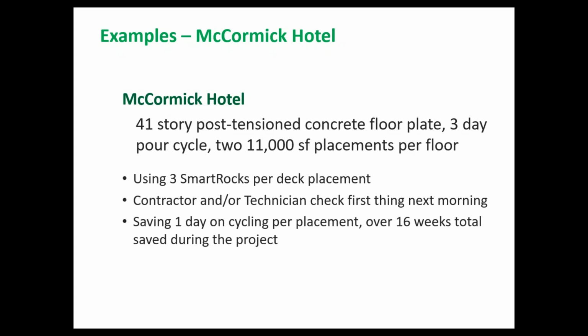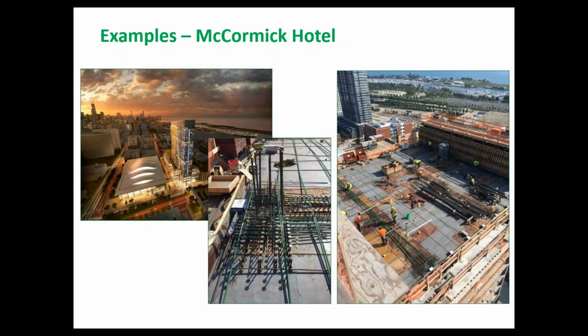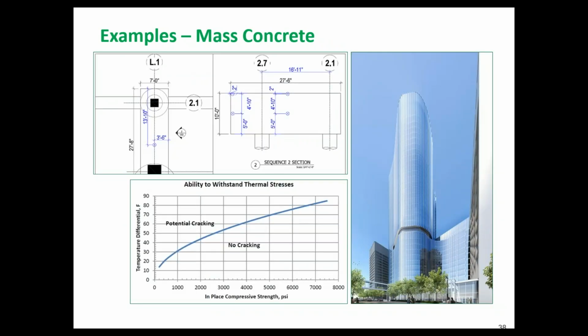That information helped them save at least 1 day per cycle per placement, and that was about 16 weeks in total saved during the project. So you can imagine how much cost saving that has for that contractor. And these are just some examples, pictures of the structure and where the sensors were installed.